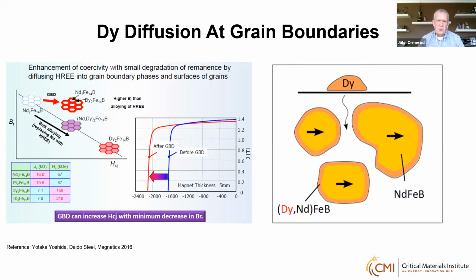So these dysprosium diffusion processes did several things. Obviously, they reduced the amount of dysprosium in the magnet. They enhanced coercivity, but at the same time, they reduced the loss in magnetization because it was only concentrated at the grain boundaries.